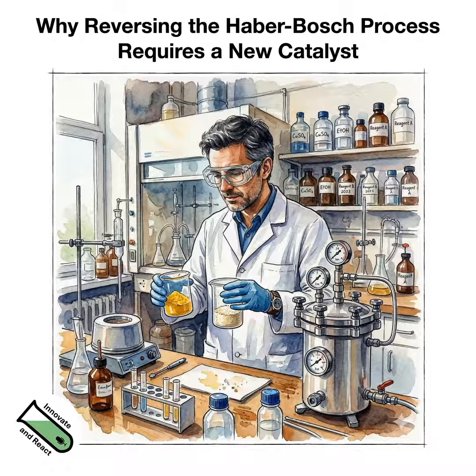And then only in the reactor itself, an applied catalyst is reduced, or at least the components that are noble enough are reduced to the metallic state. In our case, that would be iron and cobalt, and the magnesium oxide obviously would stay in the form of the oxide. And that is where the actual nanostructure or porosity of the catalyst is formed, because then it determines to what extent those metal particles grow. And what you want in the end is that they are kind of in an alternating fashion, always metal oxide, so that the oxide acts as a physical spacer between the metals, preventing them from further growth.